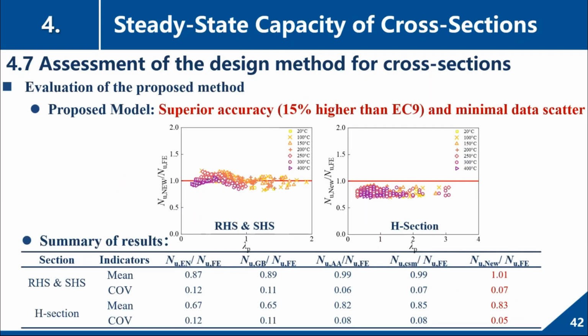And finally, these are the results of our proposed method. We can see that our method has superior accuracy, around 15% higher than Eurocode, and minimal data scatter. So this is our way to design the aluminum alloy cross sections under elevated temperature.